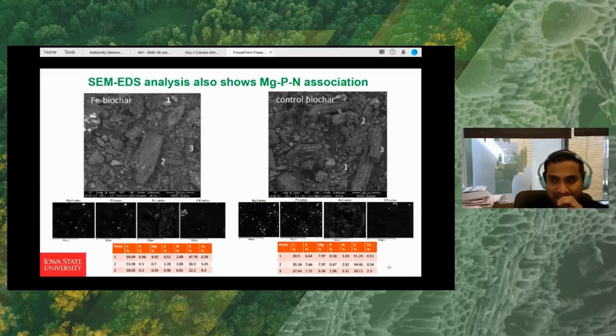In the next slide, we have shown the SEM, scanning electron microscopy, energy dispersive spectra. It also shows a significant magnesium, phosphorus, nitrogen association at different points for both the iron biochar and the control biochar. So in this study, we found that magnesium, rather than iron, is forming a complex with the phosphorus and nitrogen on the biochar surface, rather than forming an iron phosphate complex. XRD and SEM analysis prove a successful formation of the struvite mineral on the biochar surface to stabilize the nitrogen and phosphorus.